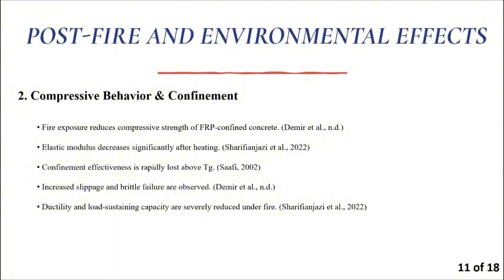And also the concrete can no longer resist axial loads as effectively as before, because fire exposure increased slippage between FRP and concrete. So we can say that instead of improving performance, the FRP confinement loses its effectiveness at high temperature. So fire exposure significantly reduced the compressive capacity and confinement efficiency of FRP reinforced concrete, leading to lower strength, lower ductility, and higher risk of brittle failure.